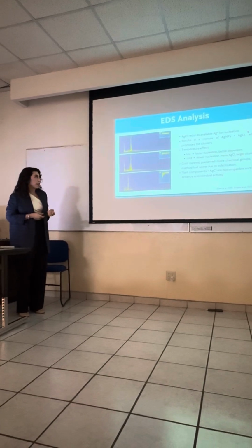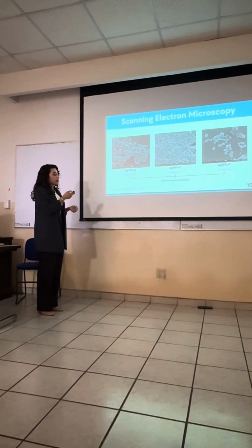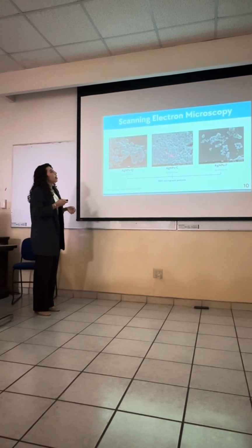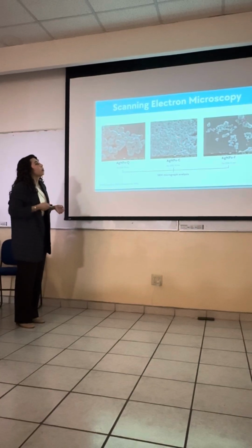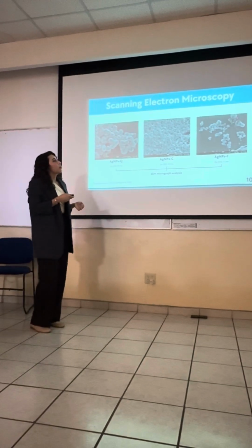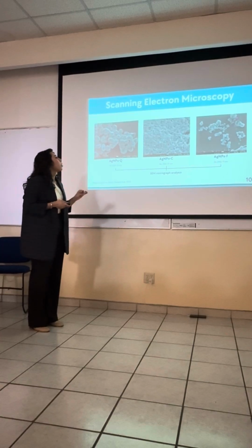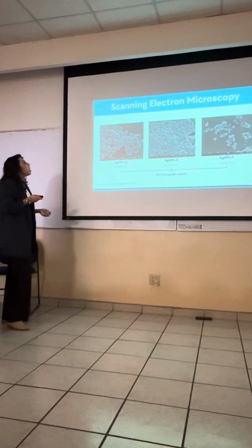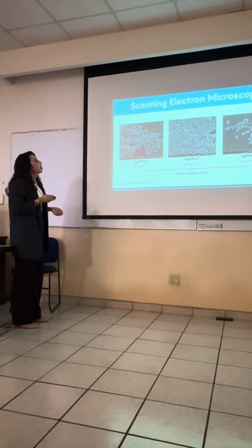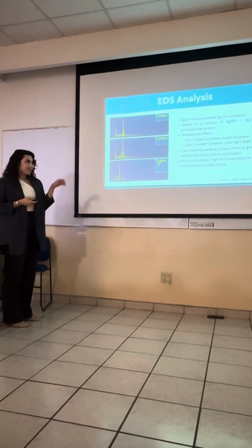And we can verify that in the micrographs that I showed you before. As you can see, in a hot method, we get much more reaction rate and dispersion of the nanoparticles. Whereas in a cold method, we're seeing that these tend to agglomerate. There are very few nanoparticles, which is one of the targets that we have, but they tend to agglomerate, and this is because of the presence of silver chloride.